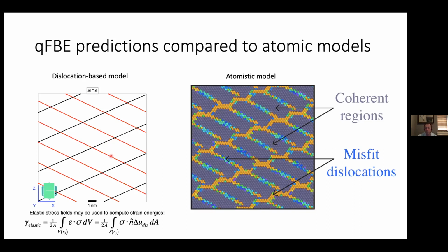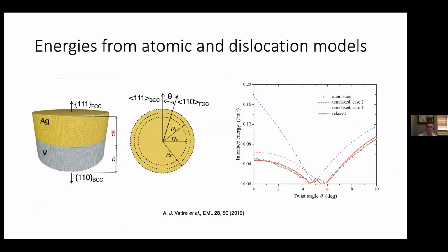Once you know the stress and strain fields around the interface, you can calculate the energy of the interface, or at least the strain energy of the interface, the contribution to the interface energy coming from these dislocations. Okay, so the upshot is that now you can make models that are quantitatively predictive, that can predict for you interface energy, for instance.